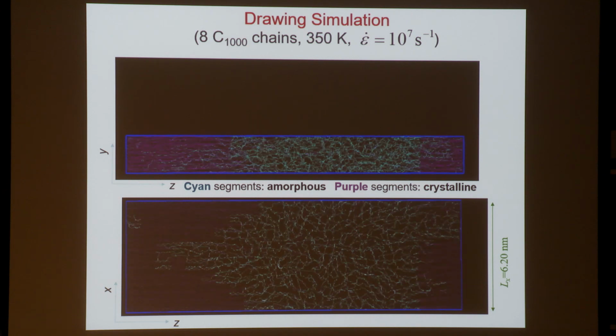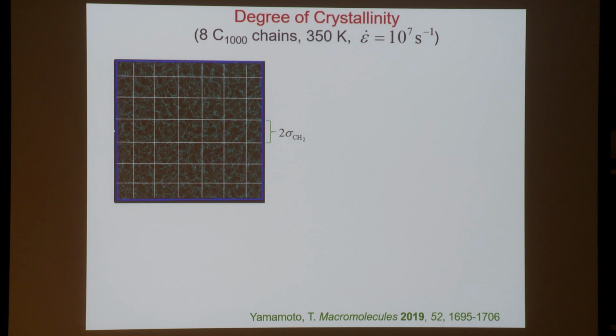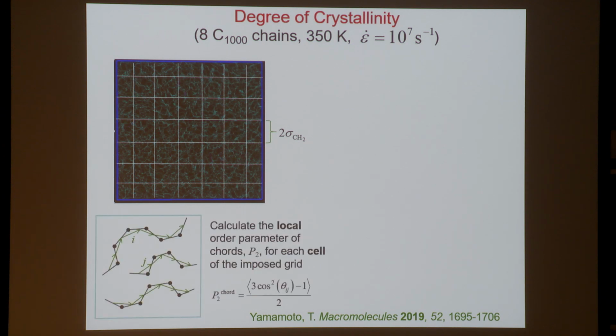So one can take this semicrystalline morphology and try to calculate the degree of crystallinity. In doing so, we have adopted methods that were proposed by Yamamoto. One partitions the system into voxels or cells of dimension equal to twice the sigma, the Lennard-Jones sigma of the methylene. Within each such cell, one calculates an order parameter from the angles theta ij between different chords in that cell, a chord being the straight line segment that connects the midpoints of two adjacent bonds. And according to Yamamoto, when this P2 is larger than 0.7, one can classify the cell as being crystalline.